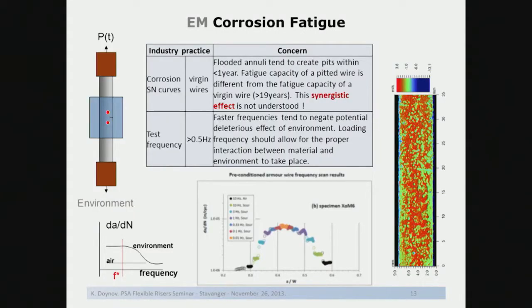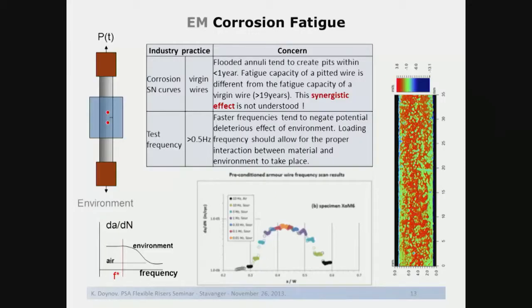So this means that the remaining of the lifetime, which is 90 plus years, instead of doing a fatigue of a virgin wire, we're going to have fatigue of a corroded wire. And another practice is that testing corrosion S-N curves typically is done at 0.5 hertz or higher frequencies. And really now the concern is that faster frequencies tend to negate the potential deleterious effects of the environment, and loading frequency should be slow enough to allow these processes to take place.